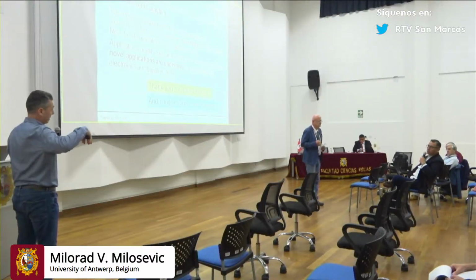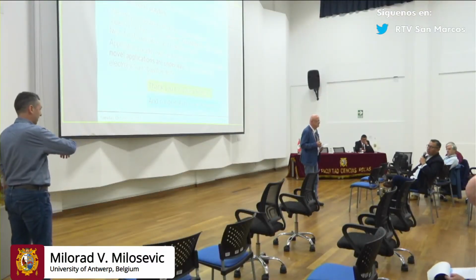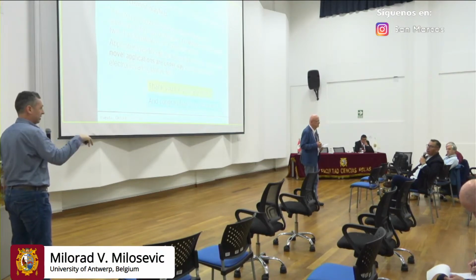Yes, exactly. So you can guess what should be the reconfiguration of the material in case of charge density wave. And then we calculate superconductivity before that, and we calculate superconductivity after that. And then we can say whether superconductivity is competing with the charge density wave or maybe not. Or coexist or compete, right? And just one, please. Is it commensurate? In this case, it's commensurate because of the small size of our calculation.